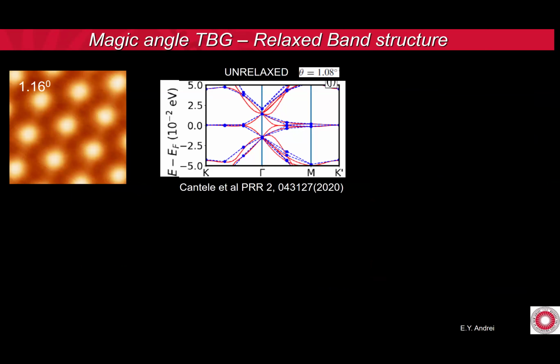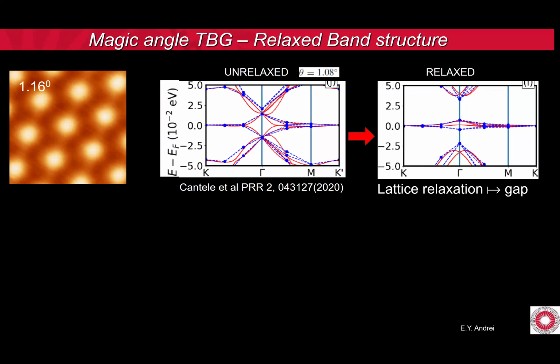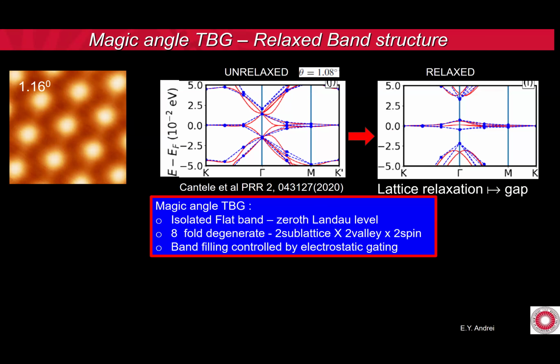When you don't relax the structure, you have a flat band, but it is connected, it's not separated from the remote band. What relaxation does for us, which is very, very important, is that it actually separates the flat band from the remote band. So what we have here is an isolated flat band. One can show that it can be mapped onto a zeroth Landau level. It is 8-fold degenerate, and therefore it has topology. It's 8-fold degenerate: valley, sublattice, and spin.